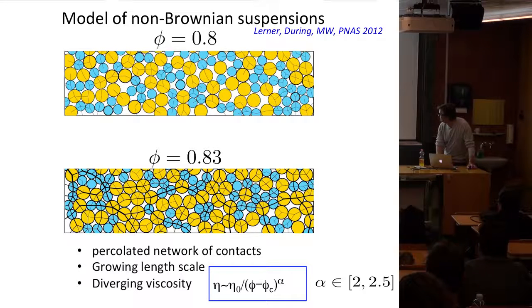Right. So what you're supposed to see here is that a very small change of packing fraction changes the dynamics a lot: here it's very smooth and not very collective. But if you look in this movie, it seems as if locally the particles were on a small scale already jammed and moving as blocks. That's a very qualitative statement, but you could get it by looking at velocity correlation, and you would see a growing length scale here. So another point that I want to make is that clearly this problem has nothing to do with percolation, because even here, when you're here and here, you're not jammed, and you still have a percolated network of contact.